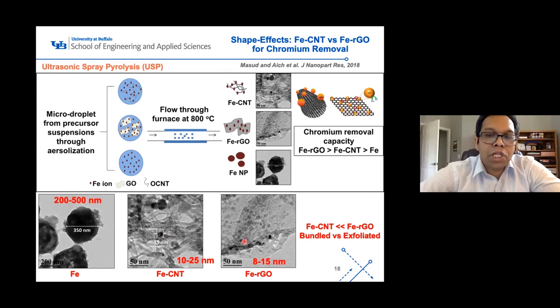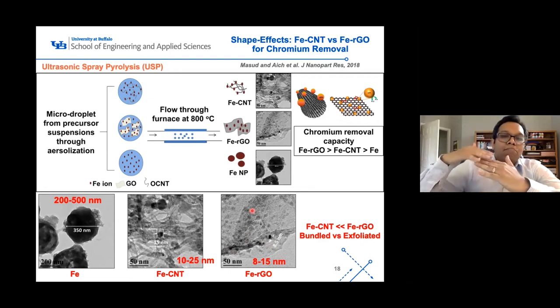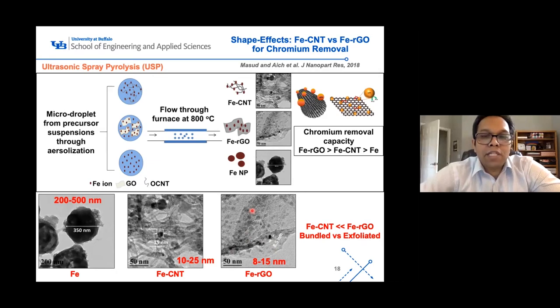They have an exfoliation case. So each individual graphene sheet will have, on top and bottom, both sides exposed with metal nanoparticles on them. So the chromium can get easy access to the surface. So that's what happens. So we believe that's why the reactivities are different. And we conclude that the iron graphene structure, the two-dimensional structure, gives us better performance for contaminant removal.